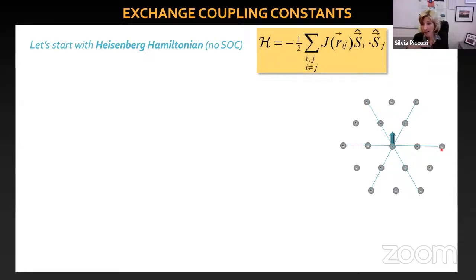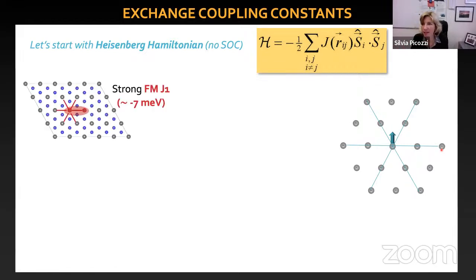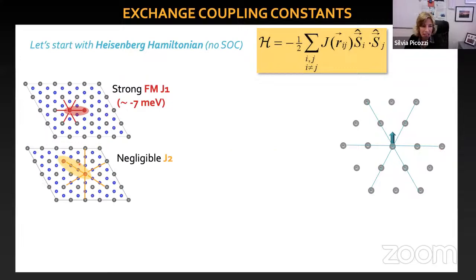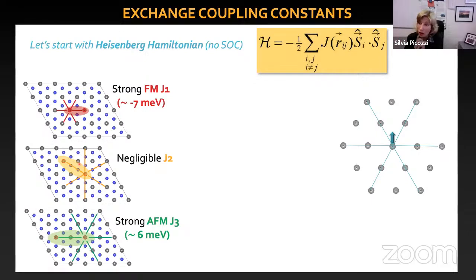And so we move to the DFT characterization. We map our total energy, for a moment, just onto a Heisenberg Hamiltonian. And we extracted the first nearest neighbor J, which is strongly ferromagnetic, a negligible J2, this is what we obtained for nickel halide, and then a strong antiferromagnetic J3. So if I now try to place this interaction on my lattice, my first neighbor is strongly ferromagnetic. So if I start from the central spin, all my neighbors will want to be up. But already at the third neighbor, I need to have an antiferromagnetic interaction. This is what I get from DFT.